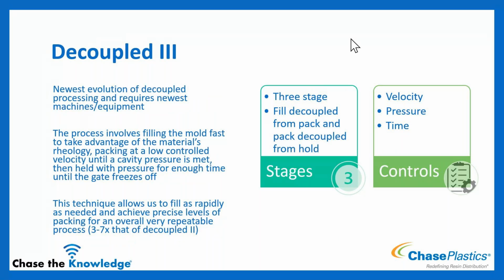From there, we moved into the decoupled three, which is what we considered the newest evolution of decoupled molding and does require some extra equipment and typically newer molding machines to accomplish. So much like decoupled two, we're going to fill the cavity under high velocity to take advantage of that material rheology and shear thinning. We're then going to pack at a low and controlled velocity to meet a set pressure. Once that pressure is generated, we can drop the velocity component so we're no longer moving the screw, but we're statically holding at a pressure now. What this does is gives us significant control over the pressure in the cavity of the tool.